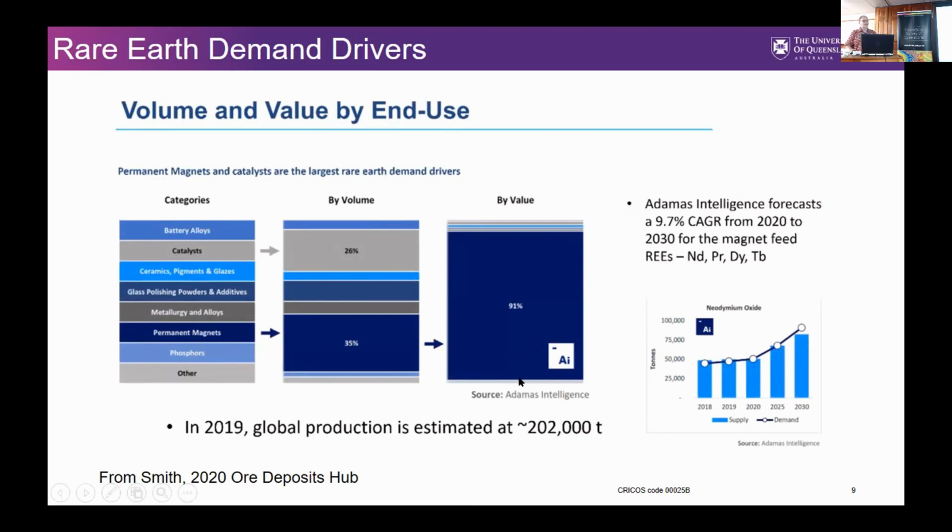So it's magnets, basically. Neodymium and praseodymium are what are really essential for magnets. And dysprosium and terbium make the magnets work at higher temperature. So they're very expensive because they're much more rare, but because of that, they're also more susceptible to substitution. But if they're not present in some way, you have to find some other way to make the magnet stable at high temperature.